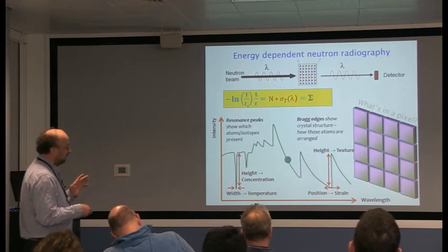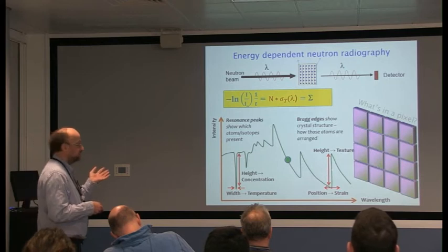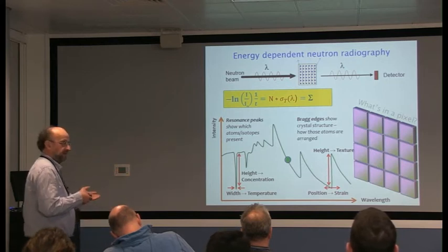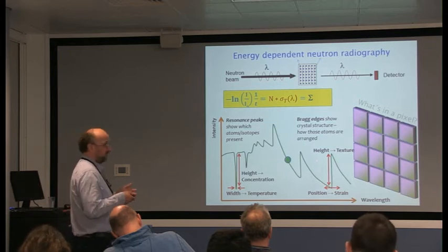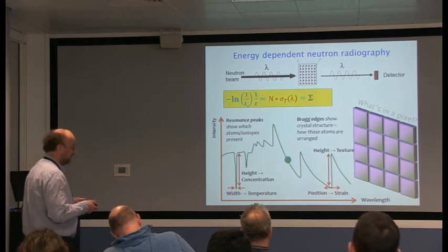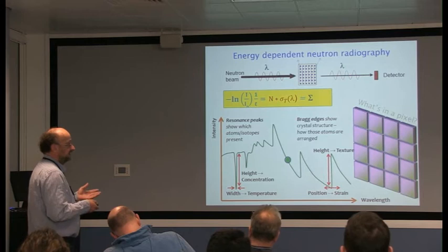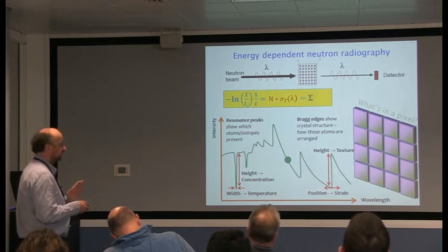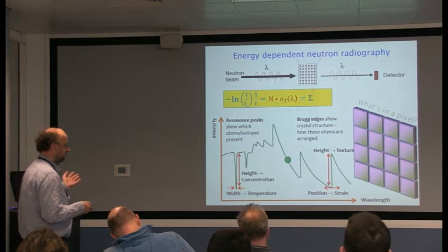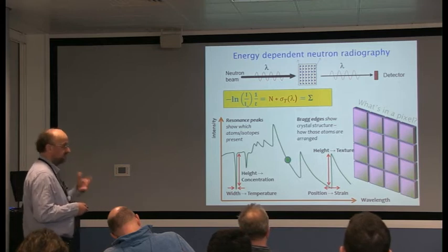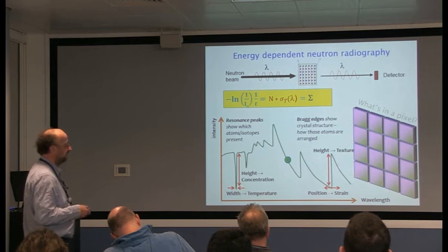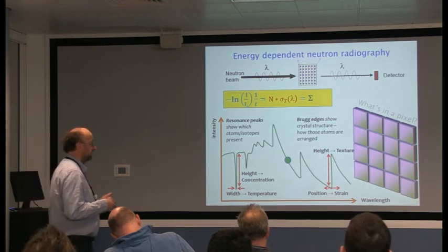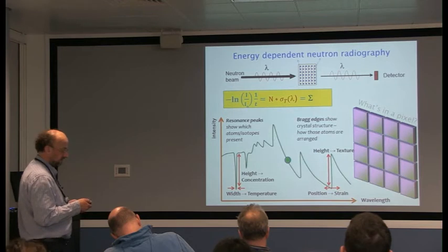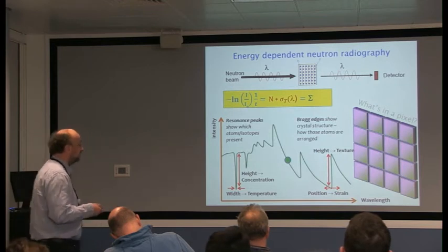And what we will observe are the so-called Bragg edges, which are basically nothing else but the effect of neutrons Bragg scattered out of the beam. So we see those as edges in the transmitted beam, and then we can analyze the positions of the edges and translate those positions into strains. We can analyze their height and relative heights and determine compositions and get information about texture of the material, and look at the width of an edge to determine particle sizes and microstrains to a certain extent.